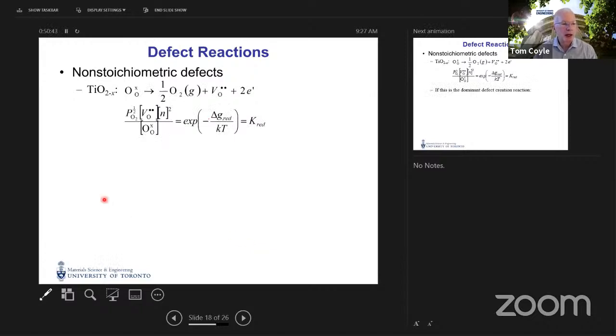So what's that look like in titanium oxide, where we lose oxygen to the atmosphere? Again, we write down the mass action expression, where now in the numerator, we have the oxygen partial pressure to the 1/2 coming from this term. We have the mole fraction of vacancies on oxygen sites. And we have the concentration of electrons in the conduction band. That's raised to the second power because we create 2 electrons in this defect creation reaction. And then in the denominator, we have oxygen on oxygen sites.